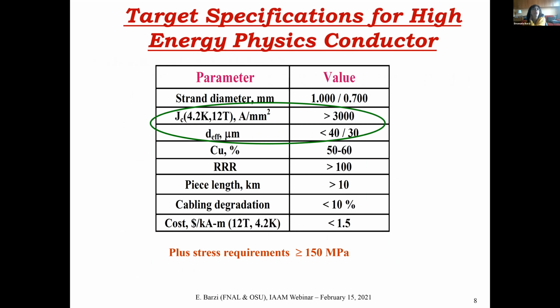So the magnet designers come to you and they say, okay, we need this feature. So for instance, they need, of course, the best current capabilities. So this is the critical current density of your superconductor. And we express it typically at helium temperature and 12 Tesla because we are shooting at very high fields, in ampere per millimeter square. So we are now on the level of 3000 ampere per millimeter square at this temperature and field. And then you see the so-called effective filament size, which actually is pretty much the size of the sub-elements of the niobium tin little elements that I showed before. And they need to be limited in size.